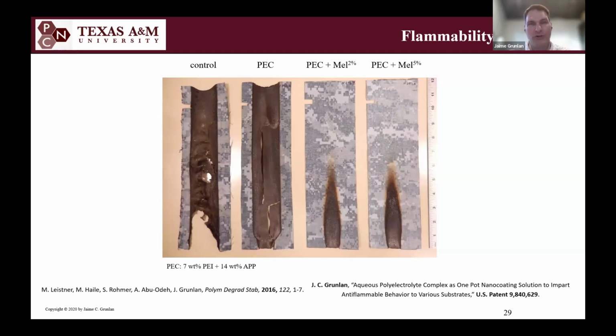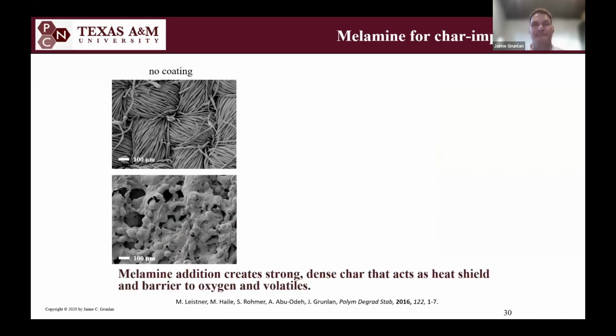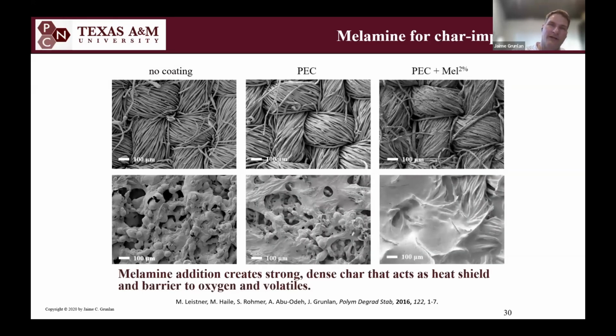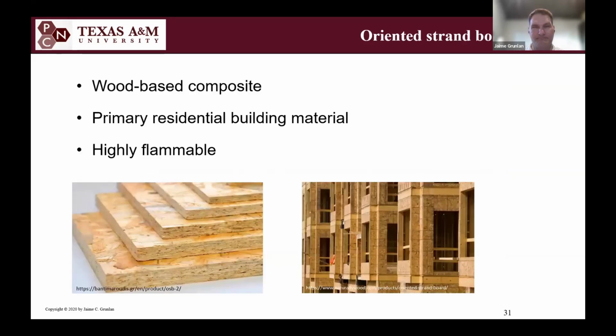And you can see with the control, you have some combination of what's called a scaffolding effect and charring, because you've got the nylon and cotton side by side. You also get some melt dripping, which is bad because it spreads fire to other places. And you can see here the improvement in the char. These are post-burn samples, SEM images, and you can see that the char is the most complete once the melamine is present. The melamine polyphosphate acts almost like a heat sink. It actually reduces the temperature of the burning somehow during the process.